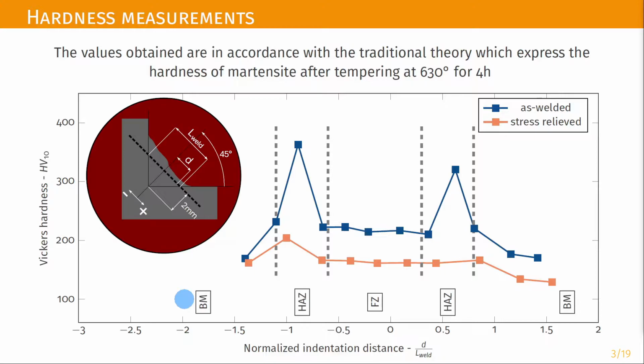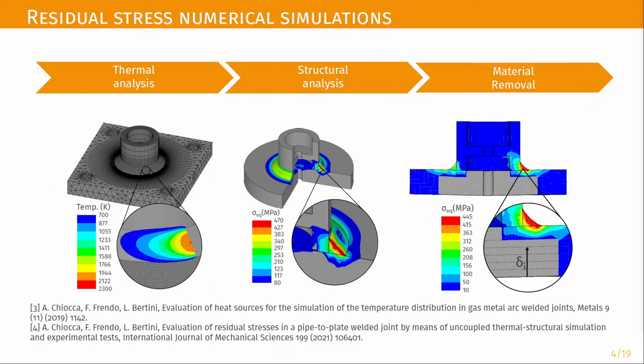For the sake of clarity, only hardness measurements have been presented here. However, even from a microstructural point of view, differences were found due to the thermal process, with a grain coarsening close to the weld seam region.